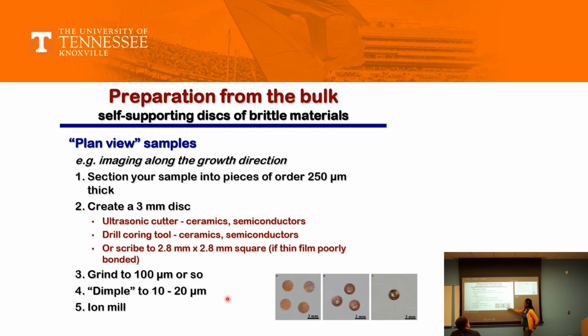First of all, it would be very tough to have such a 3 millimeter disc. And then to dimple it, you have to grind it to 100 micrometers, and my sample would break. 100 micrometers is itself very thin, and from 100 micrometers I am creating something at the center, which would further break. So I don't see the purpose of doing it. With metals, you do it. We also have students in our group who work on ceramics. So for you guys, what is the technique?